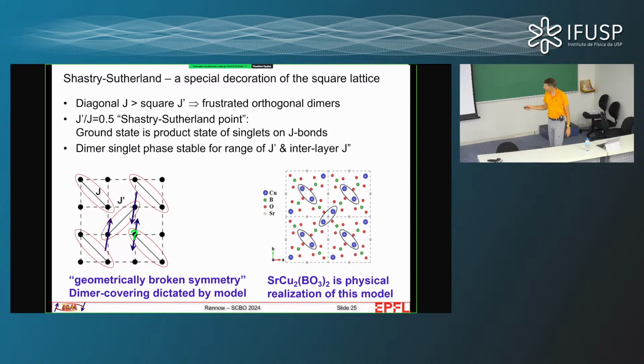Okay? And what is really interesting is that there is this material, strontium copper borate, which contains copper, oxygen, strontium and boron in such a pattern that it is topologically equivalent to this square lattice, exactly the Shastry-Sutherland model. SrCu2(BO3)2. Okay, so that means that we can now actually do experiments on this system here and compare with what theorists might be able to calculate. Unfortunately, this is the only material we know that realizes this model. It would be great if we had a few others where we had greater variability over, for instance, the ratio between J and J prime, etc. But this is what we have.